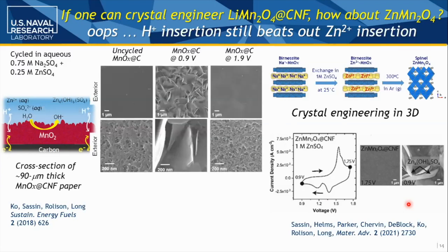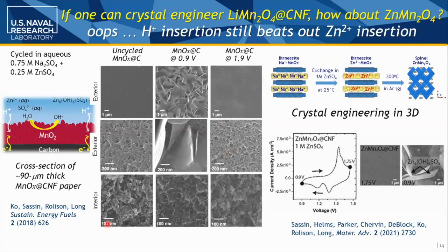And of course, she did some of her exterior interior showing that, yes, you make all of this salt, but when you come back to 1.75, you've cleared it out. And she likes cross sections. So you can see you've got that porous interior that looks like it's starting to fill. But then once you've come back to 1.9 in this case, it's gone away. So these are questions we can ask without a lot of the confounding implications of being in a powder composite electrode structure.